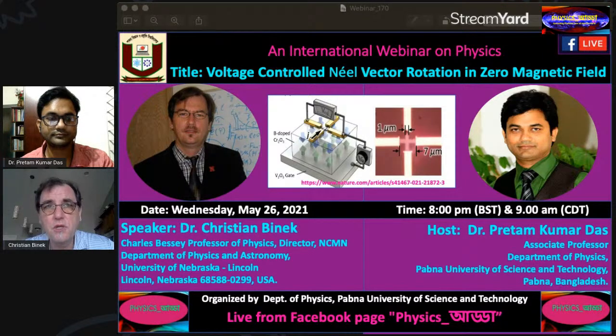Whenever you cool down a ferromagnet and you come to a temperature where the thermal energy, k Boltzmann T, and the microscopic interaction energy between the spins, which is on the order of the exchange energy, become comparable, then order can start. Depending on details such as dimensionality and so forth, long-range order can happen, and that's a very exciting phenomenon. For virtually all applications of magnetic systems, you need ordered systems, so you always need to be below an ordering temperature.